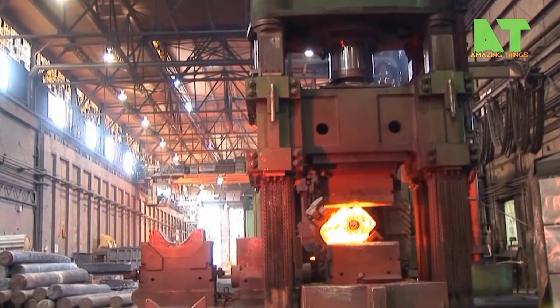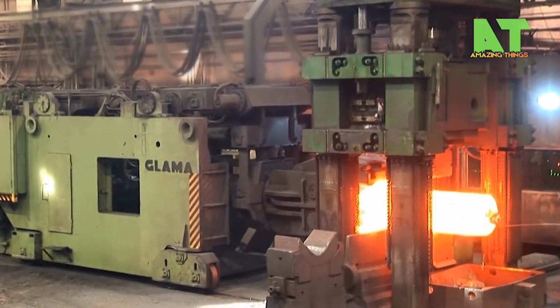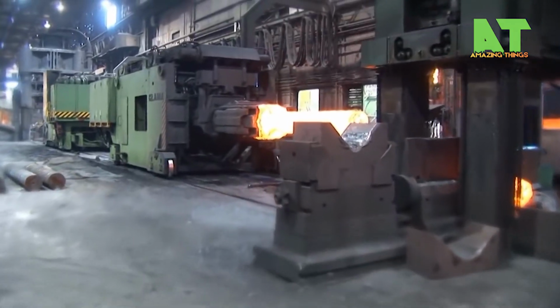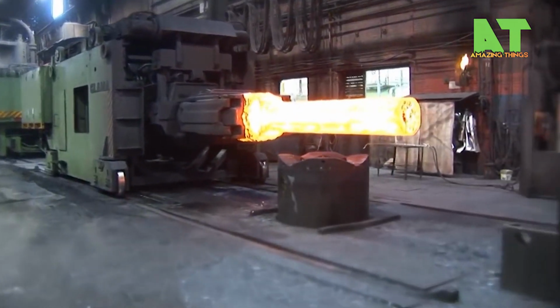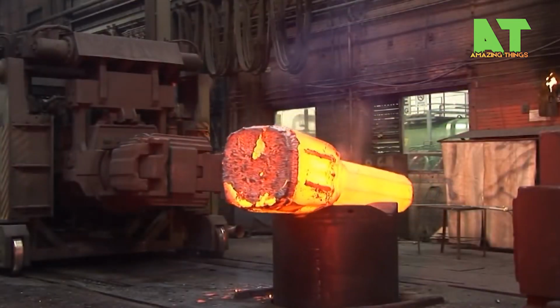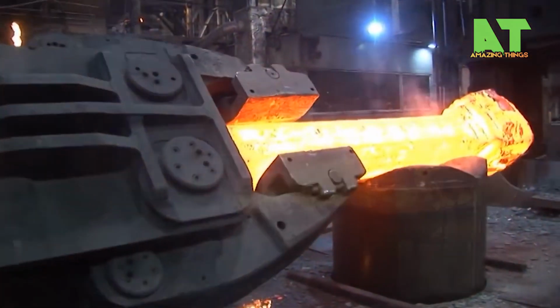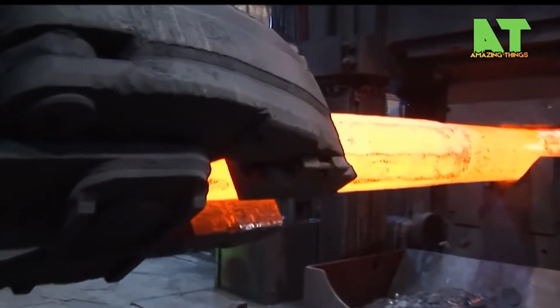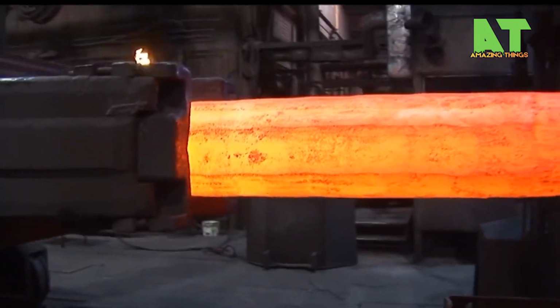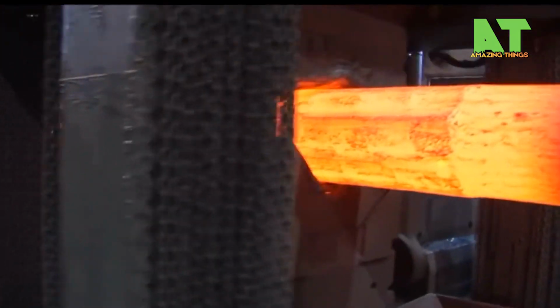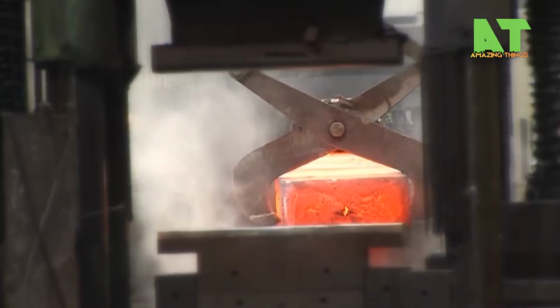Each forging stroke compresses the grain structure, eliminating internal voids and creating a dense directional fiber flow that gives forged parts their legendary toughness and fatigue resistance. After forging, parts go through controlled heat treatment cycles, annealing, normalizing, quenching, or tempering, tailored to meet precise mechanical property requirements.